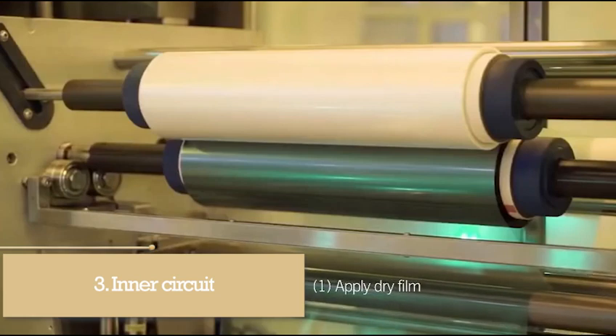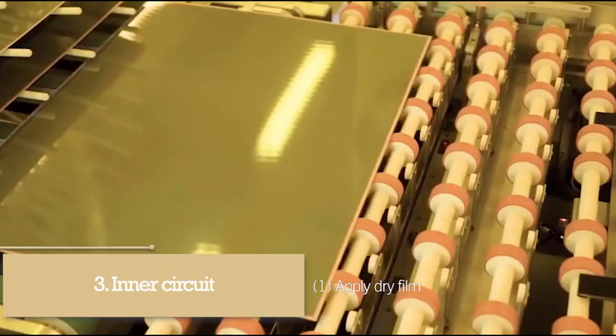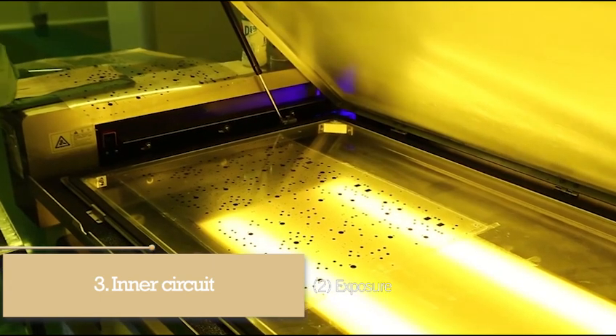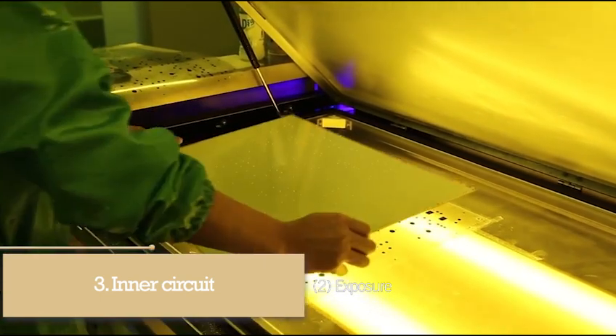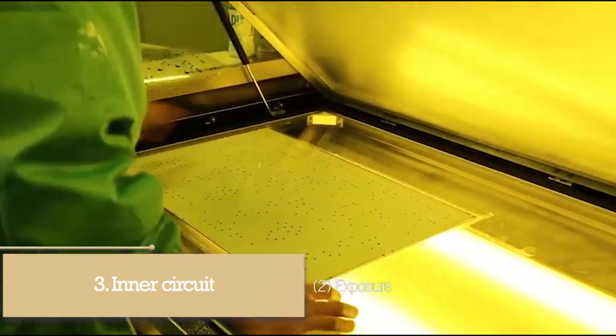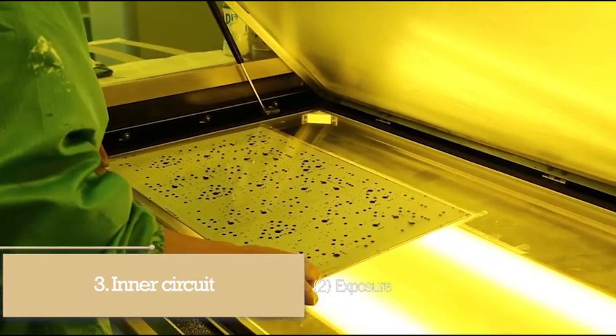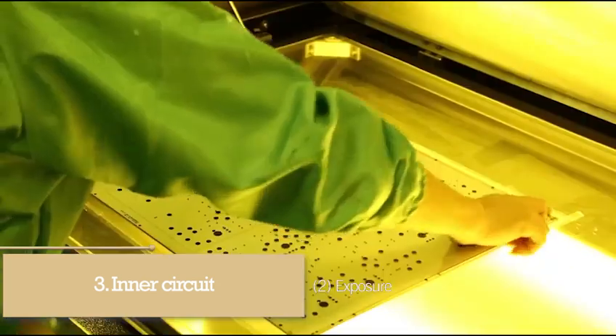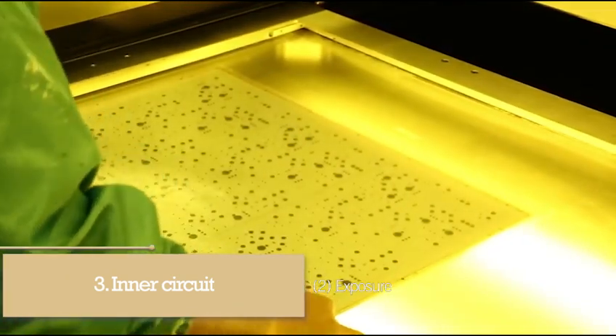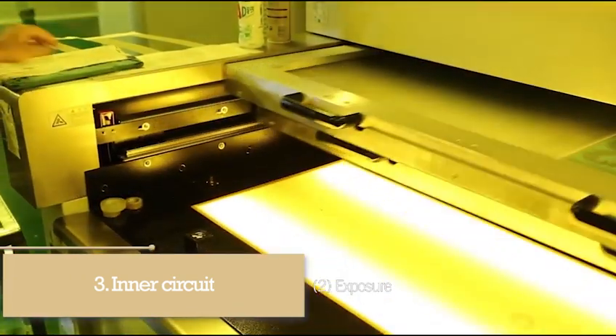1. Apply dry film. The treated substrate is pasted with a dry film to facilitate subsequent exposure production. 2. Exposure. Align the film negative with the substrate on which the dry film has been added on the exposure machine. Use ultraviolet light to transfer the pattern of the film negative to the photosensitive dry film.